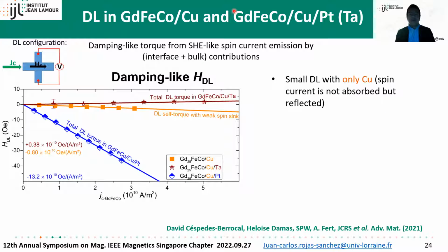And here I summarize this study. In orange, I show the result of the damping-like effect in this gadolinium iron cobalt copper bilayer. We can see that there are small values. When we now have a three-layer, when we add the tantalum, this is also small, but changes the sign. And we can see that when we have a three-layer with platinum on top, platinum also being a good spin sink, we have a large effect, a large variation.